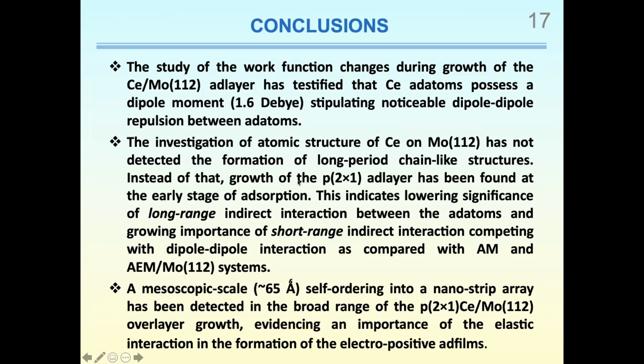A mesoscopic scale, about 65 angstroms, self-ordering into a nanostrip array has been detected in the broad range of the primitive 2x1 cerium on molybdenum overlayer growth, evidencing an importance of the elastic interaction in the formation of the electropositive adsorbate films.